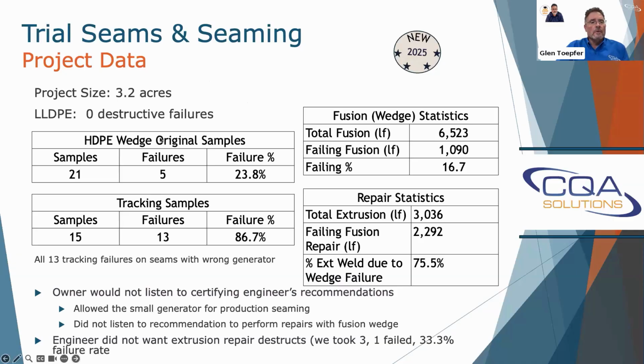But this is a project data, 3.2 acres. We had the HDPE wedge weld, original samples 21, five failures, so there was a failure rate of roughly 24%. But again, all the failures showed up at the beginning of the project. So they did switch over to a different generator, the big generator. But in the meantime, we had tracking samples on those seams. There were 15 tracking samples, 13 failures, and an 87% failure rate.